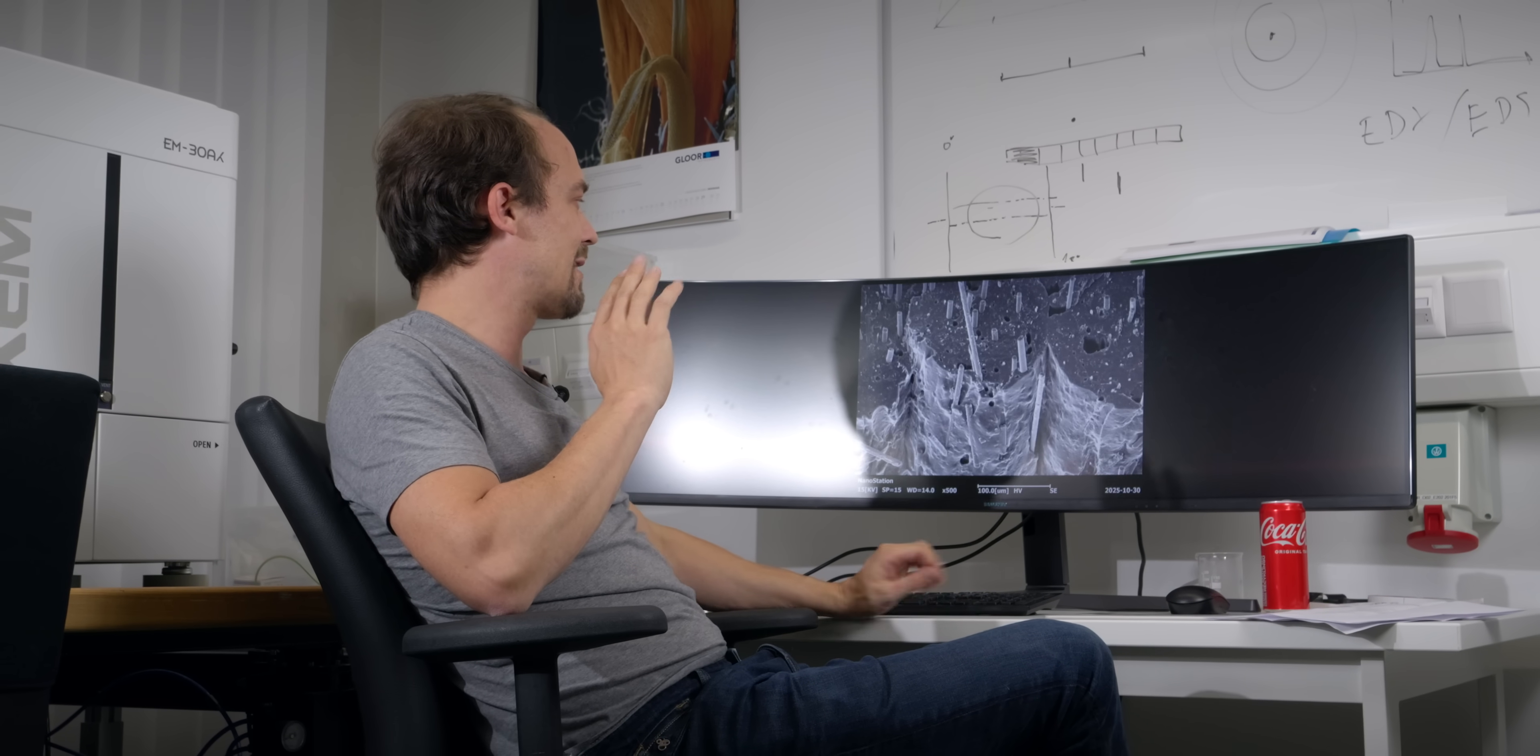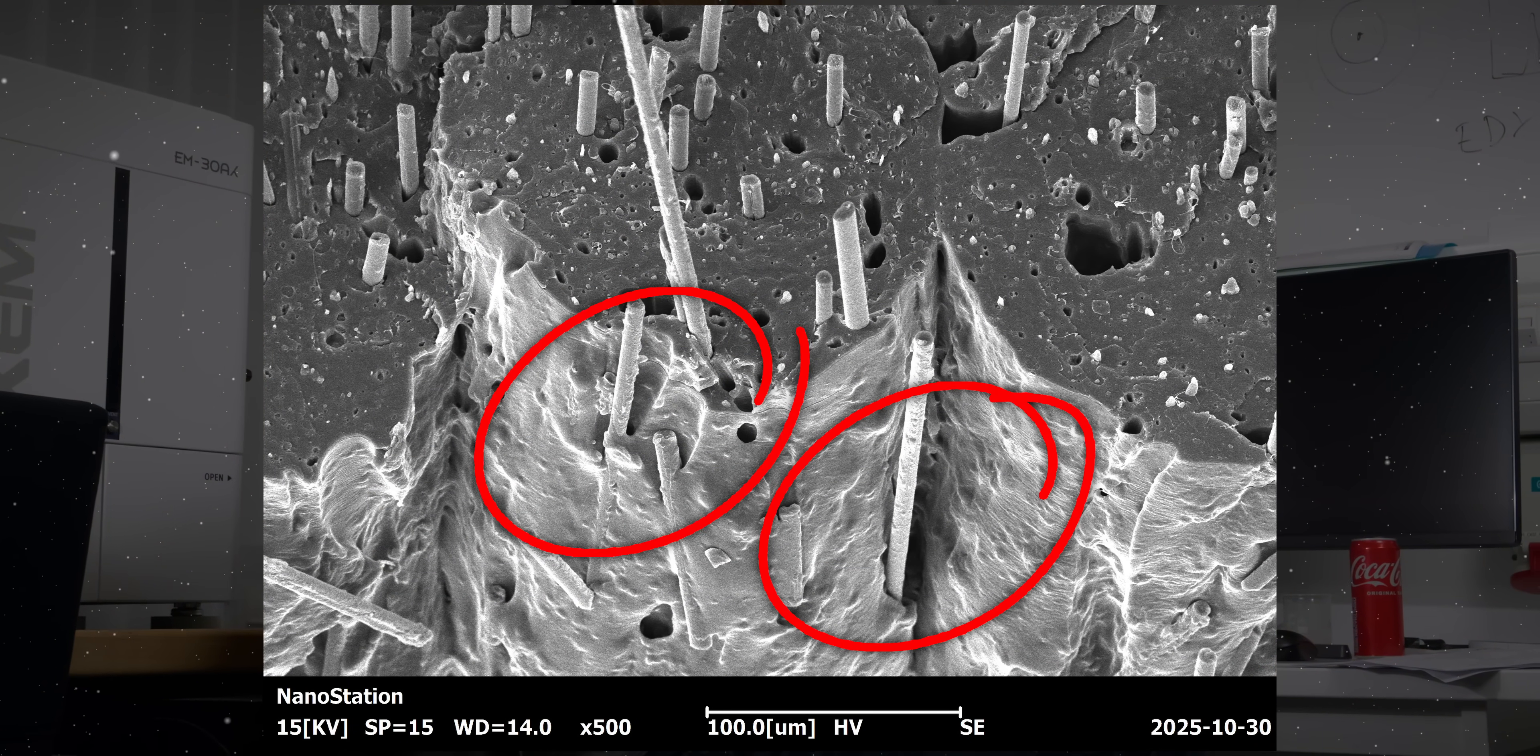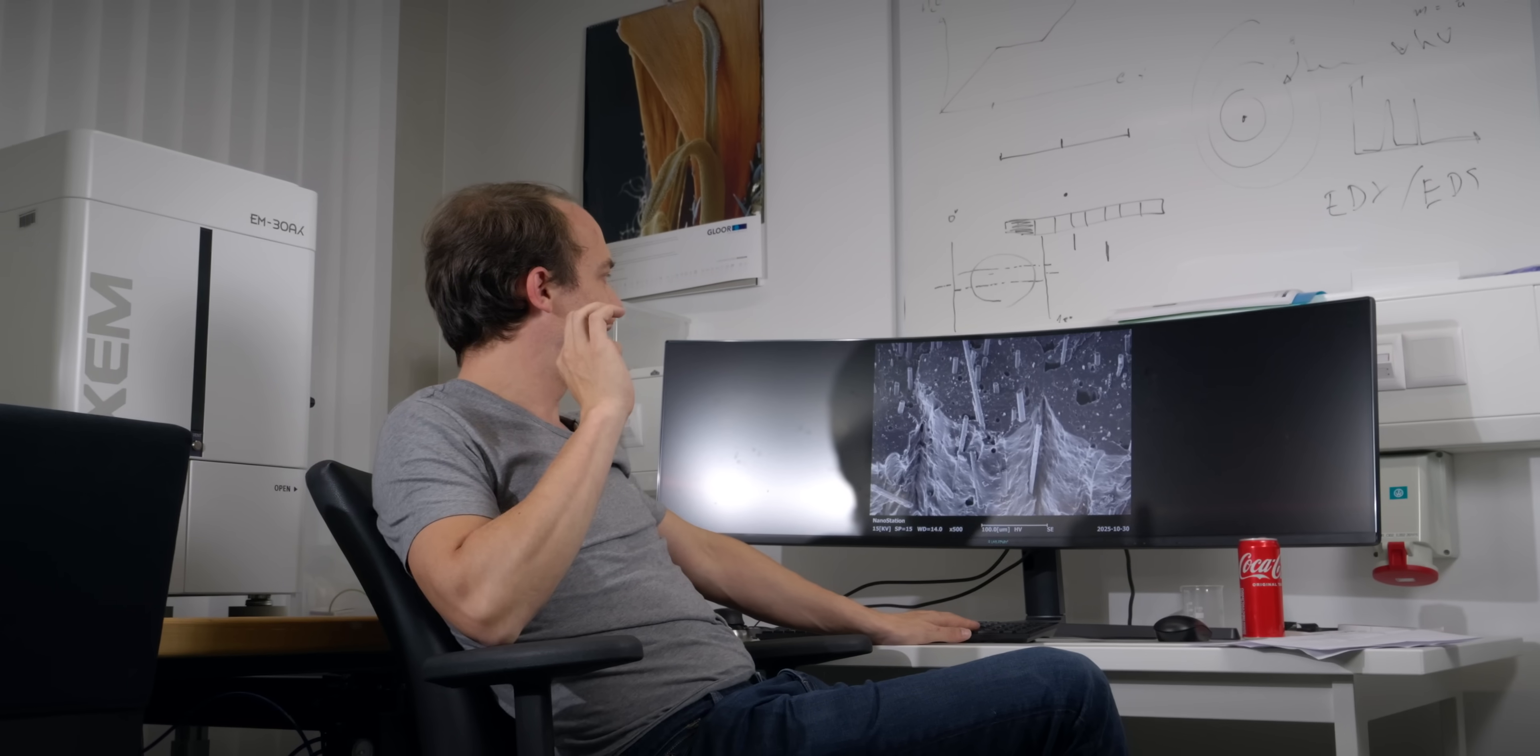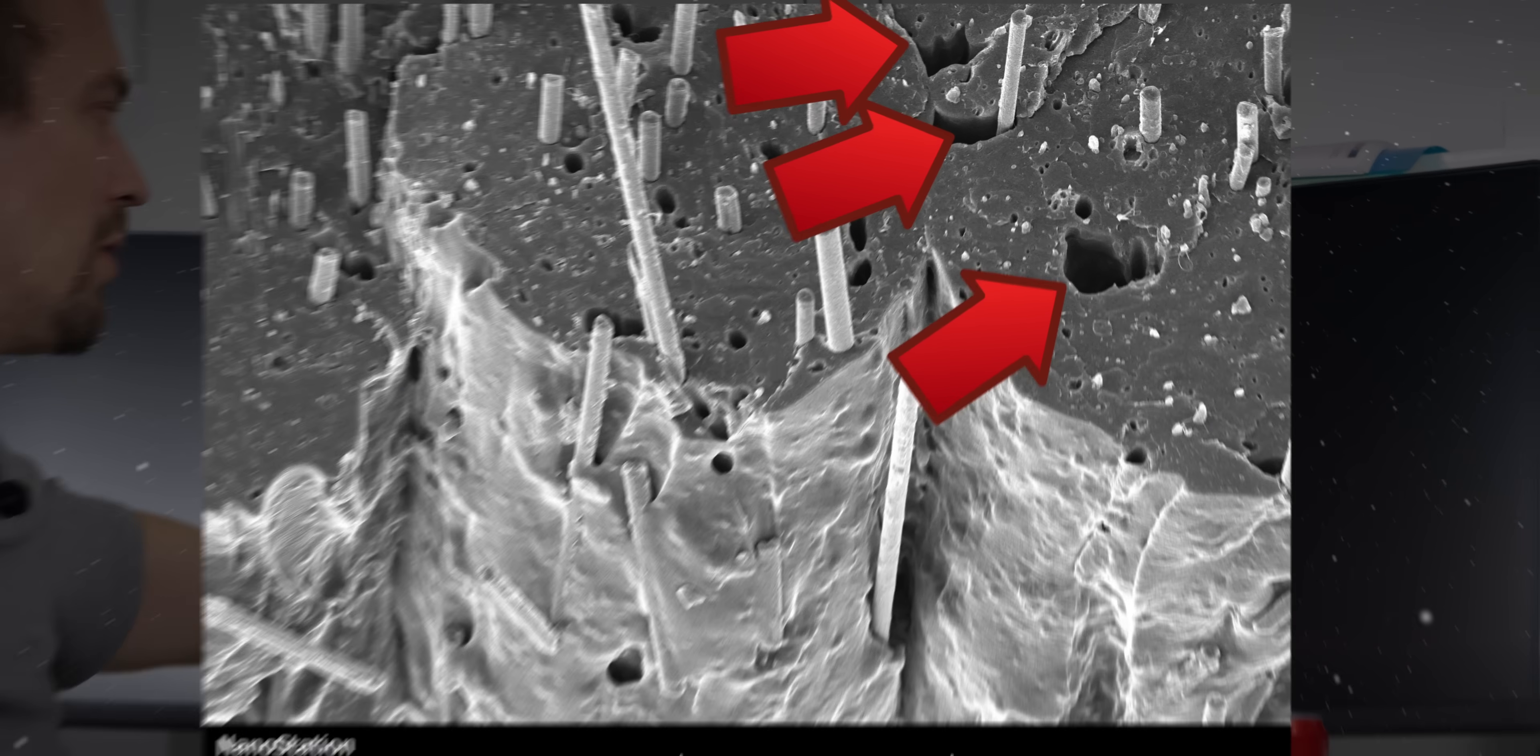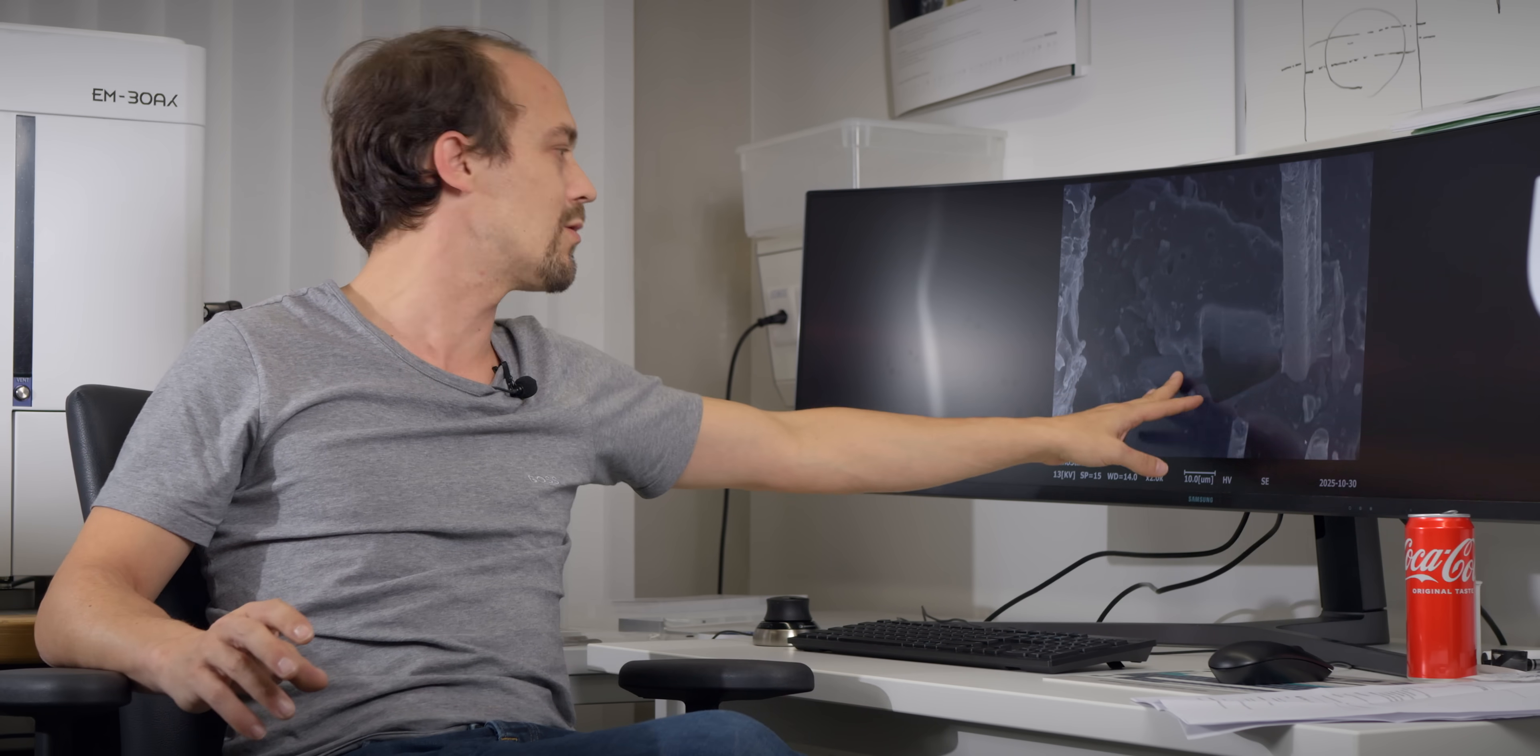So if we zoom in a little more here, you can actually see that I was quite right. The carbon fiber does not stay within the polymer itself. It actually gets everywhere. Here you can see on the outside, the carbon fiber sticks out everywhere. If it's here, it's also in between the layer lines itself. But one thing that surprised me a little bit is if you look at this image, you have all the carbon fiber, you have holes where we ripped out carbon fiber, but you also have those huge voids. My PLA was dried, so that can't be moisture voids. If we zoom in a little, you can see they are everywhere—around carbon fiber, not around carbon fiber, and they're actually quite big.